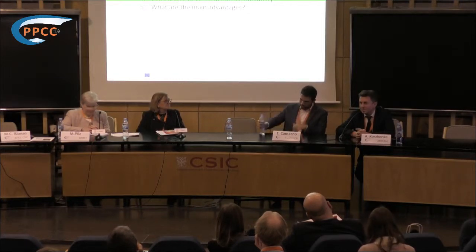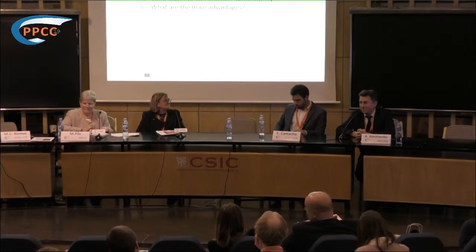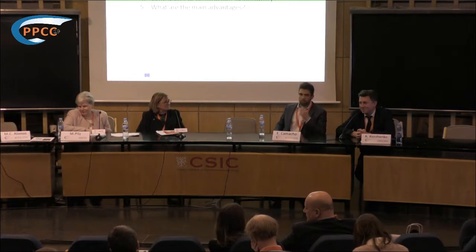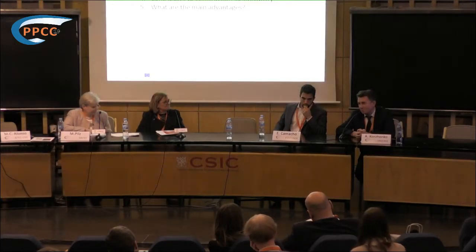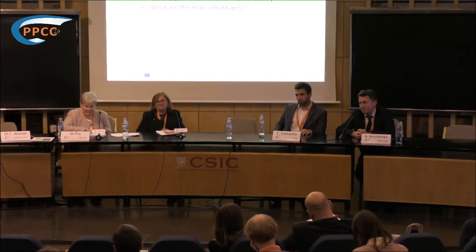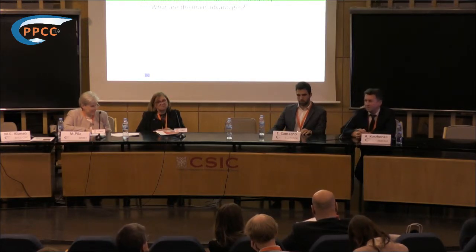Okay, so that's really the opposite side of what we may expect. It is, actually. And this increase in the resistance is because of the more compact structure of the cement rock, and ionic transport is also reduced. So you have fewer pores, it's more compact. It's about half a decade of difference sometimes that we usually observe for the conductivity. Okay, thank you very much.